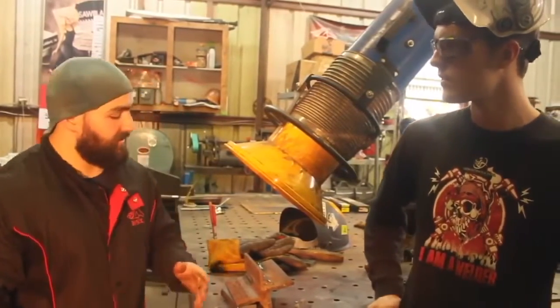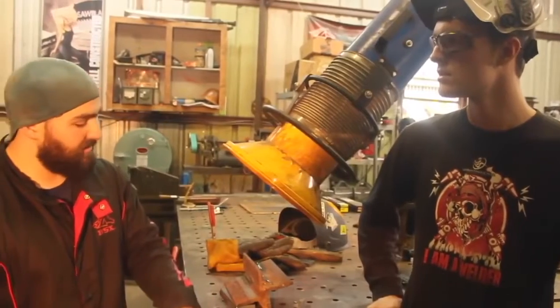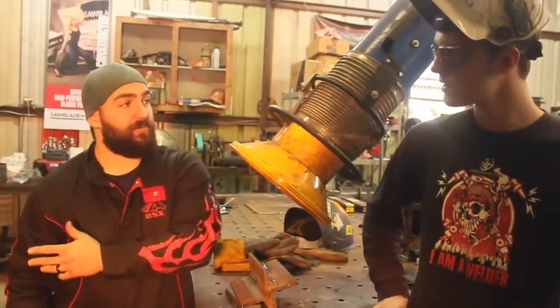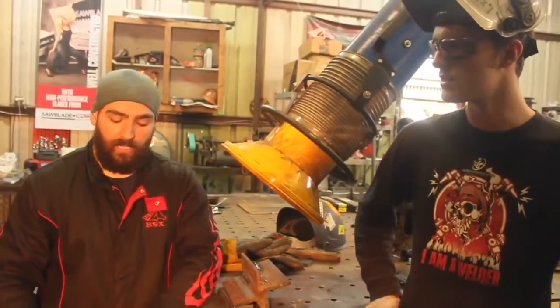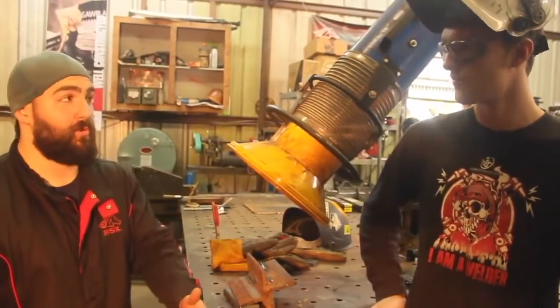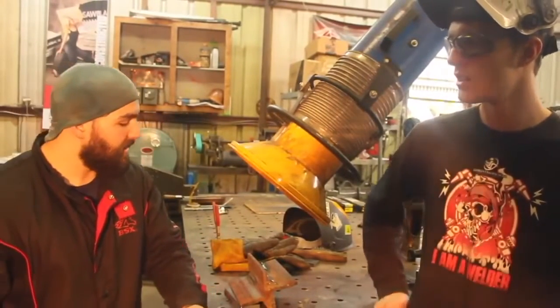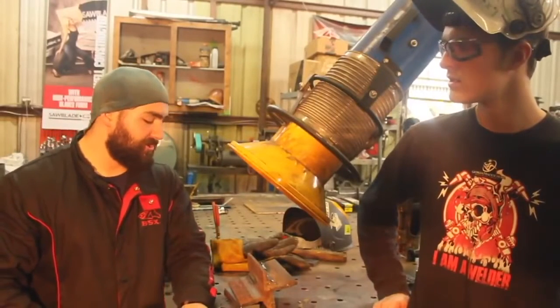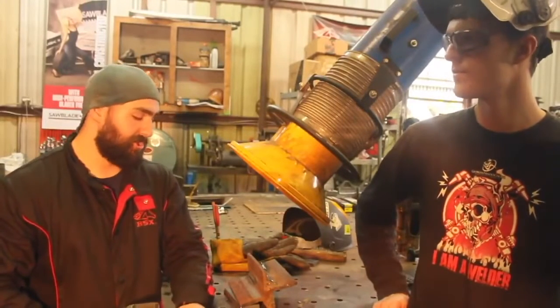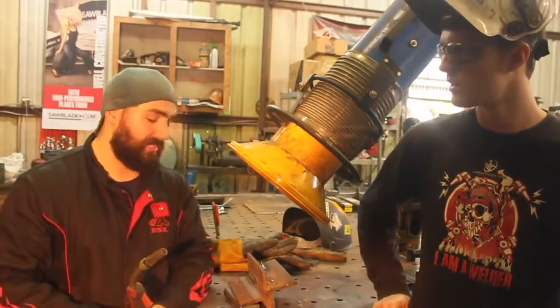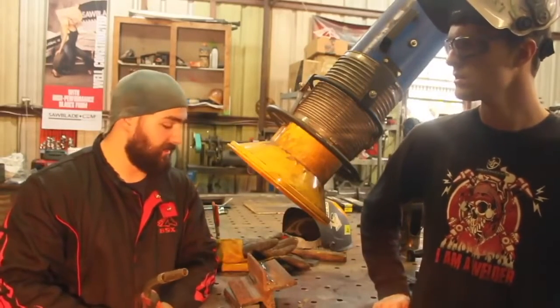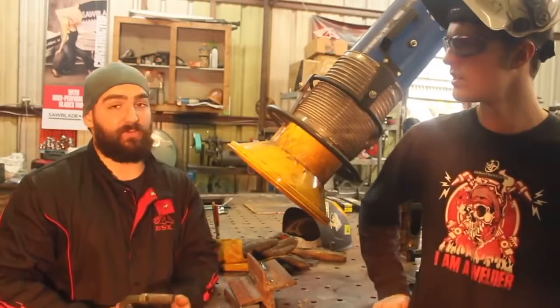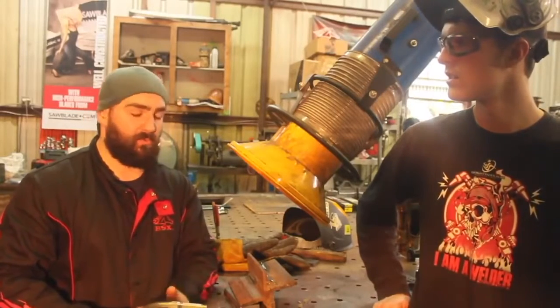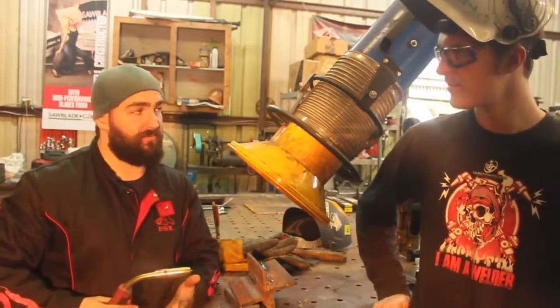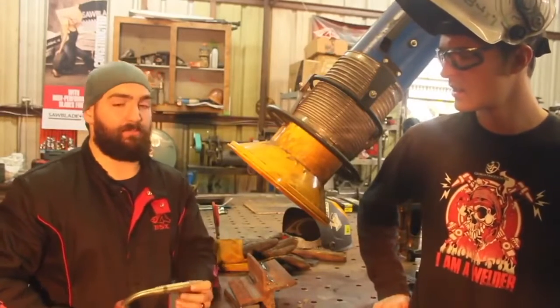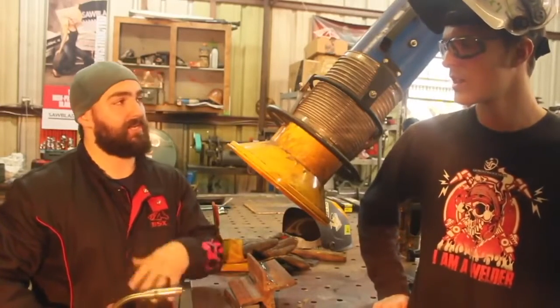So typically if my students have surface porosity, wagon tracks, wormholes, things like that, the first thing I'll do is look at their flow rate, check the gas out, and check to see if their voltage and their wire feed settings are correct. But more or less it's usually just an adjustment in gun angle, an adjustment in checking your gas, or an adjustment in checking your voltage. So those three variables really can cut that down. Also, the biggest one that I run into for novice welders is really their stick out is just too far away. So they're just getting a little bit of porosity from the shielding gas not completely covering it.